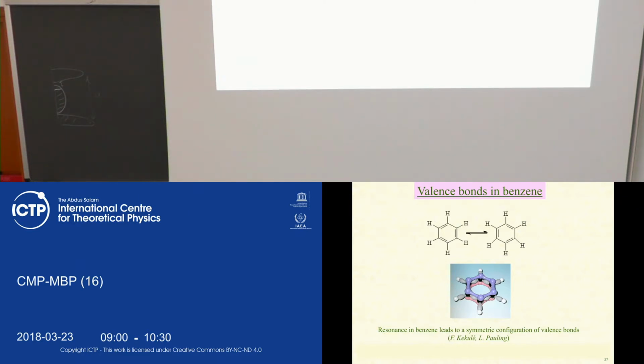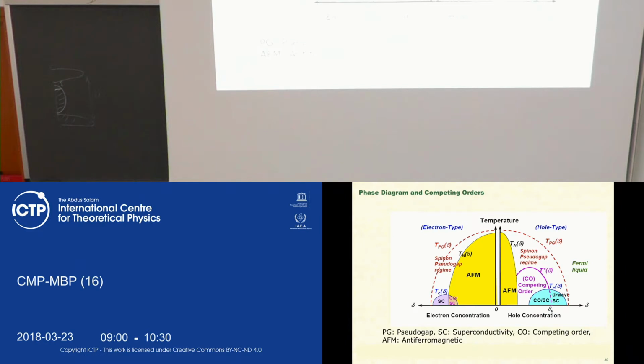Anderson used the same terminology and the same ideas in order to borrow it and utilize it in high temperature superconductivity. What then happens, according to Anderson's theory, is that in your antiferromagnetic state, when you dope it, some spin liquid is formed. So this is not a magnetic state at all. So you dope this system until you destroy the superconductivity. So this is the phase diagram.